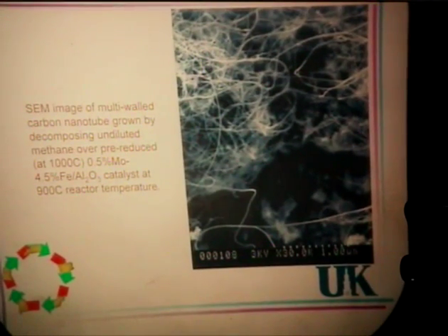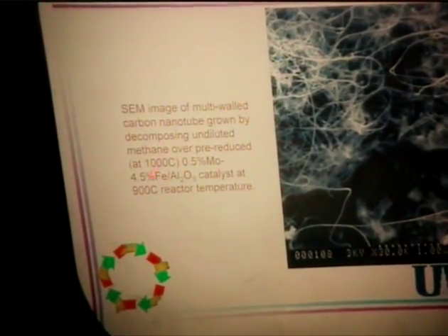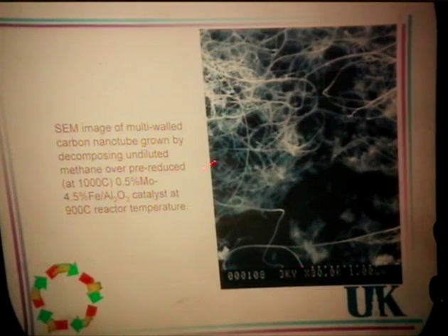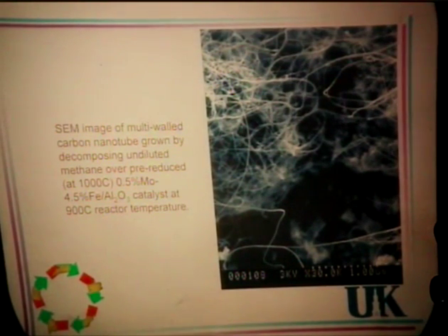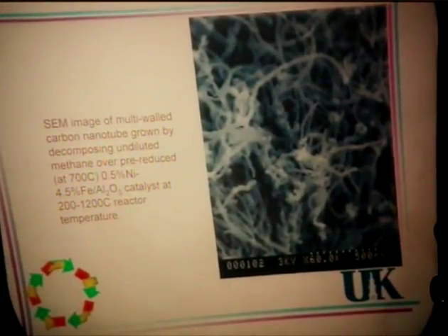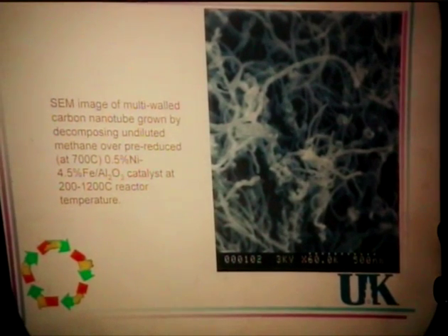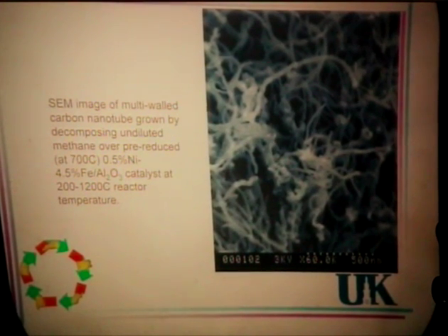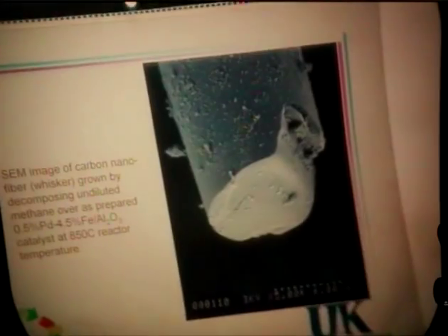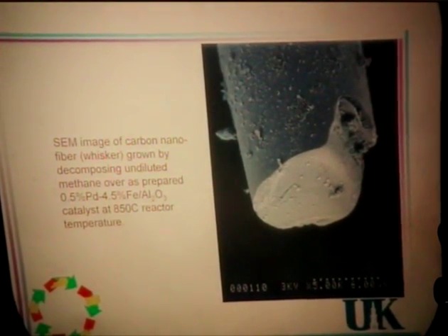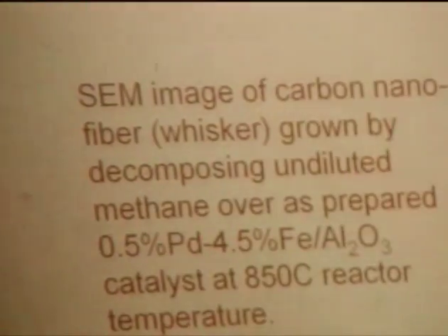Here is an SEM image of multi-wall carbon nanotubes grown over the moly iron bimetallic catalyst at 900 C. Here is another SEM picture of multi-wall carbon nanotubes grown over the nickel iron catalyst. Here is carbon fiber grown over the palladium iron catalyst, as prepared, at 850 degrees centigrade.